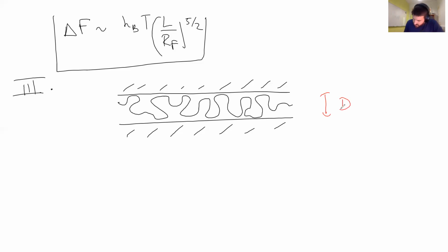And naturally, remember, so far we did the semi-dilute solution, there was a natural length scale for the blobs, which was xi, the typical distance between crossings with other chains. Then in the previous example, what we did is to pull on the system, and so the force was defining a length scale when compared to thermal energy. Again, there was a natural appearance of some blob. And here, the natural length scale is D. So D will define a blob.